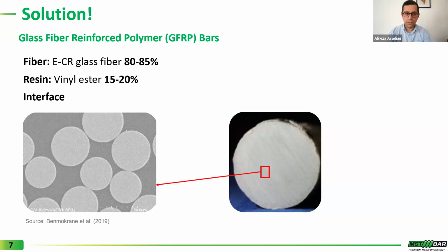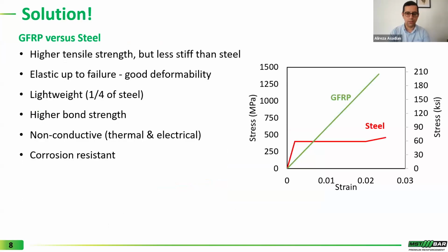We use the latest generation of glass fiber called ECR glass fiber. And the resin that showed a very good durability for construction application is vinyl ester resin. In a cross section of MST bar or any high modulus GFRP bar, there is around 80 to 85% ECR glass fiber, and the remainder of 15 to 20% is vinyl ester resin.